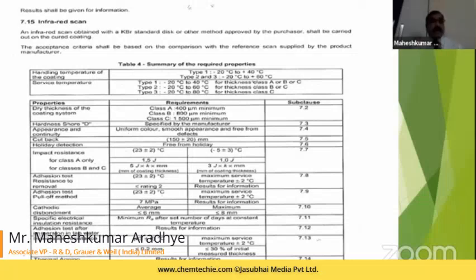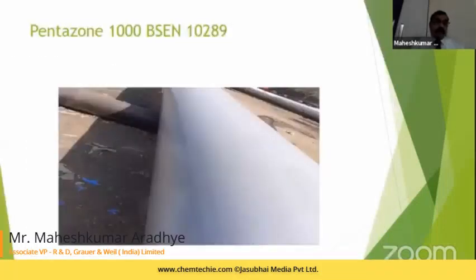This is the summary of the required properties, which talks about the dry film thickness, the Shore hardness, the appearance, the adhesion onto the cutbacks, the impact resistance, adhesion pull-off test requirements, and cathodic disbondment test requirements. These are all given in BS EN 10289. So, how do we say that this particular coating works onto the system? We developed a coating system as Pentazone 1000 BS EN 10289. We gave this name to our product Pentazone 1000 for the ease of understanding.